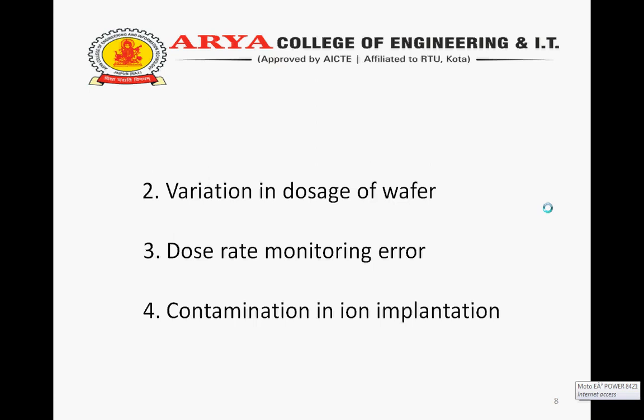If the particles fall on the wafer before implantation, they will screen the wafer from the implant. A later clean may remove the particle, but its unimplanted shadow remains behind as a virtually undetectable killing defect. Most particles are caused by improper wafer handling, improper pump down procedure, clamping procedure, the use of unfiltered gases, etc.